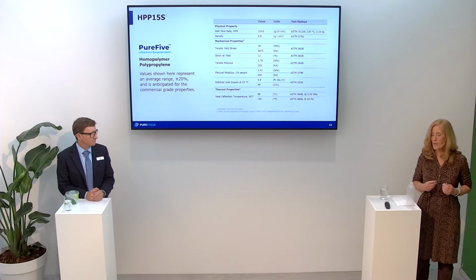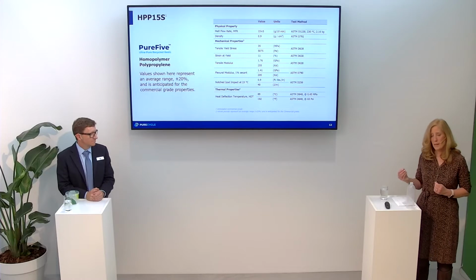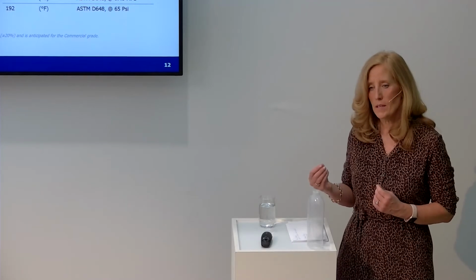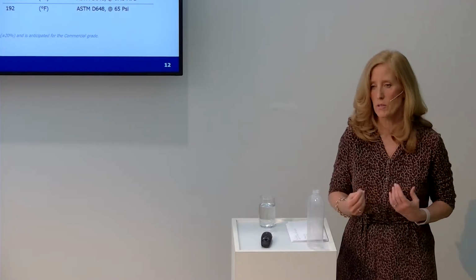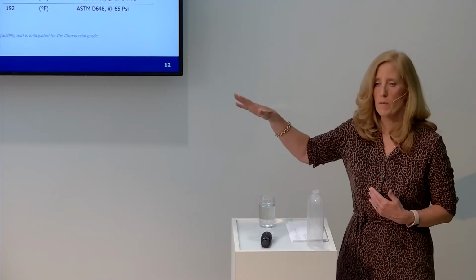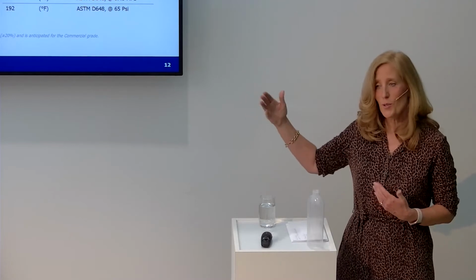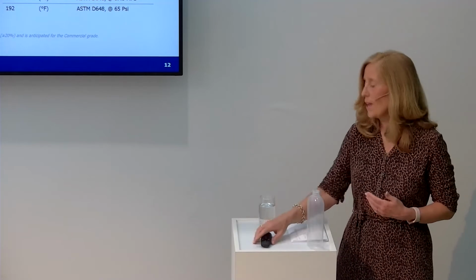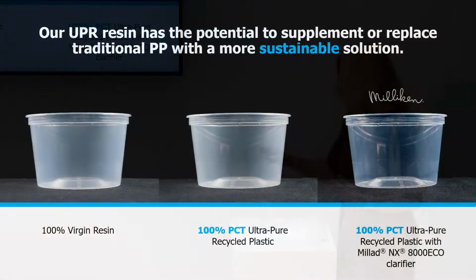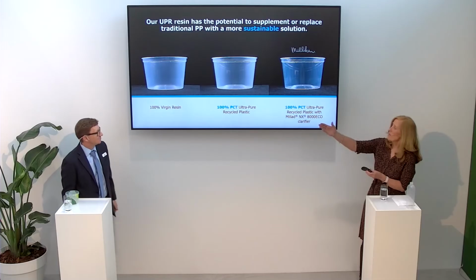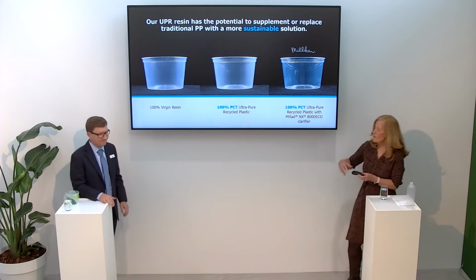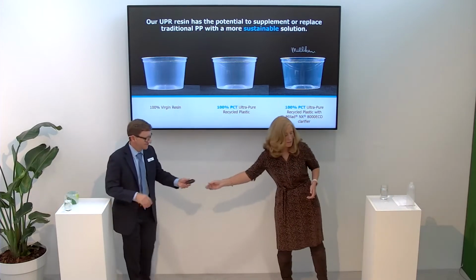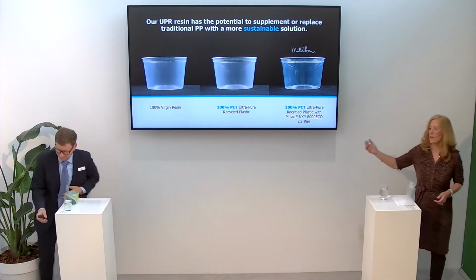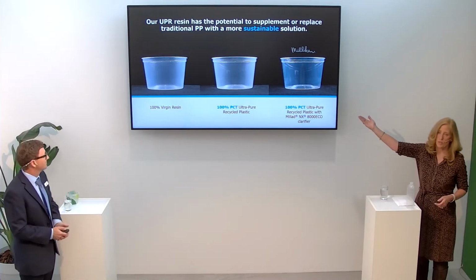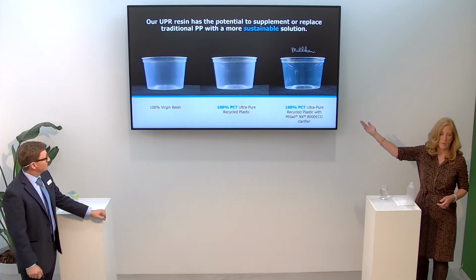So the real benefit of working with Milliken is that they can produce additives and impact modifiers and melt flow changers that can allow us to adjust the melt flow of the 15 melt lower or higher. So the good news is we have this great partnership. And with that, I'd like to turn it over to Scott. In fact, he can even talk about the fact that you've seen them at the booth and that we have samples of virgin, 100% PureCycle, and then 100% PureCycle with Milliken additives, and you can see the difference in what they can bring to us already with clarifiers.